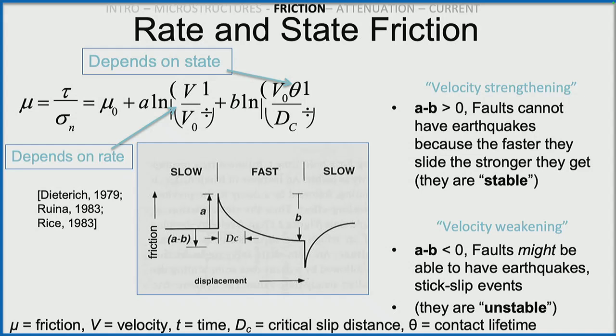There's a velocity dependence and a state dependence to friction, and the thing that I wanted to focus on is the stability, which is determined by this A minus B property. The way we measure that is that we run an experiment where we're sliding at some constant velocity, and then we do a bump up to a higher velocity. So this velocity step happens. What's the response of the system? Well, it'll be going at a constant steady state friction, and then it will have this immediate direct effect. It'll jump up. But then the friction will evolve to a new frictional value. And whether that will be lower than the first value or higher determines this A minus B. This is important, and the reason people care about this is because it tells you whether your system is just going to creep stably, or it might have an earthquake or a stick slip.